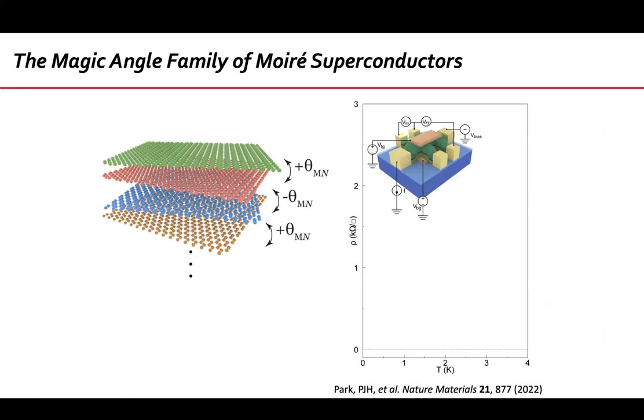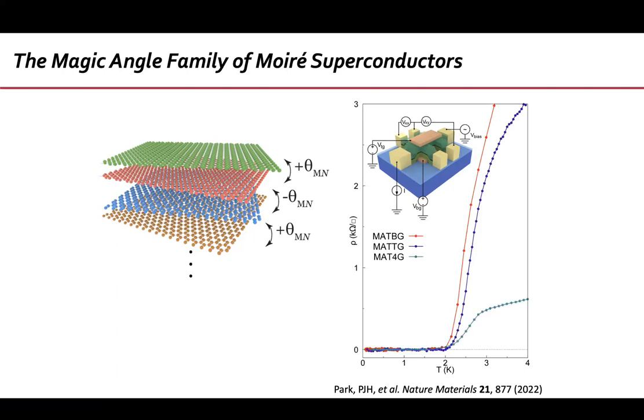So we set out to try to measure this thing. Very patient and persevering graduate students. If you measure our best magic angle twisted bilayer graphene in terms of Tc, it is this one; for trilayer it is this, tetralayer is this, pentalayer is this. So this is a family of robust superconductors. They all superconduct. In fact, it turns out the yield gets better the larger the number of layers, surprisingly.